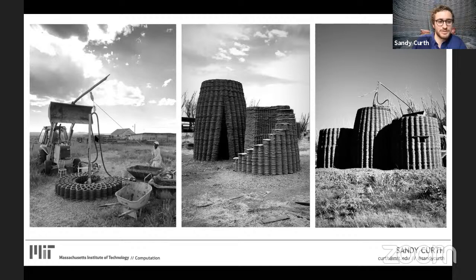Here you can see we're doing some hose management with local infrastructure, a tractor, and mixing material on site. The material itself was dug in the field right behind these images. You can see our first stair, our first attempt at a door. We began experimenting with a few things like decreasing layer height relative to slope in a domed structure to improve layer-to-layer adhesion, which a number of people do at different scales and different materials.